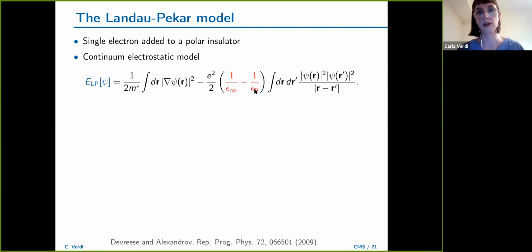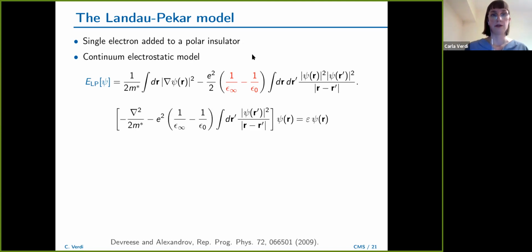And you see it is crucial here that there are these two constants. One is epsilon infinity, and this is the so-called high frequency dielectric constant. So it includes the screening only due to electrons. And this is the so-called static dielectric constant, which is kind of a misleading name. But basically it includes the dielectric screening of both the ions and the electrons. Now you can see that if the material is non-polar, then these two epsilons are the same. And so this term vanishes. But in a polar insulator, this is non-zero. And once we have this total energy functional, basically, we can write a Schrodinger equation by minimizing this with respect to our wave function and introducing a Lagrange multiplier, this epsilon here.